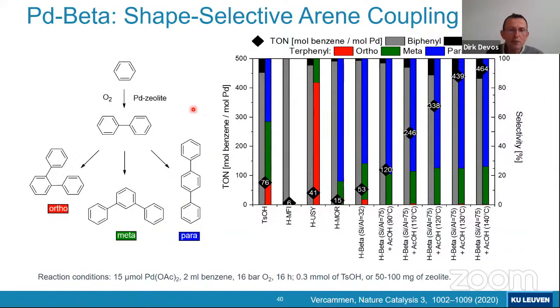Toluene is not the only case in which we have such selectivities. This is just some other data to show that this selectivity is pretty general. For instance, if you couple benzene, then of course the main product is biphenyl, and there is no positional selectivity in biphenyl. But you could go on to produce some terphenyl, and then you see, for instance, that in this reaction with the beta-zeolite, within the terphenyl fraction, which is not too much, again, the para product is the dominant one.